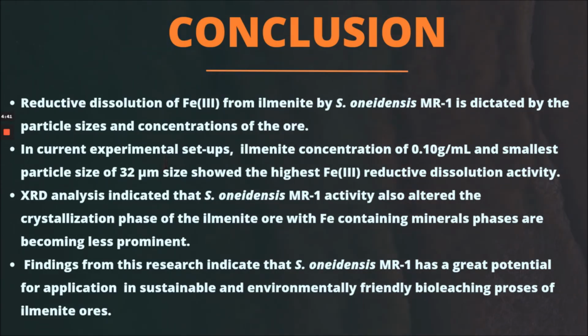In conclusion, the bioleaching dissolution process was highly influenced by both particle size and concentration of ilmenite ore. The optimum concentration and particle size in this experiment were 0.10 gram per ml and 32 microns respectively, which showed incredible dissolution activity. SEM showed the transformed surface of the grain, meanwhile XRD indicated the altered crystallization phase after the ilmenite ore was treated with Shewanella oneidensis MR1. Findings from this research indicate that Shewanella oneidensis MR1 has great potential to overcome the issues that were stated in the problem statement.